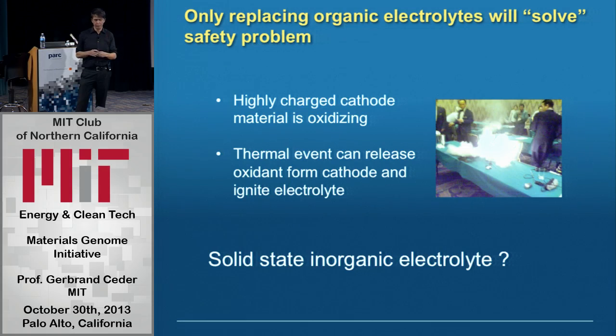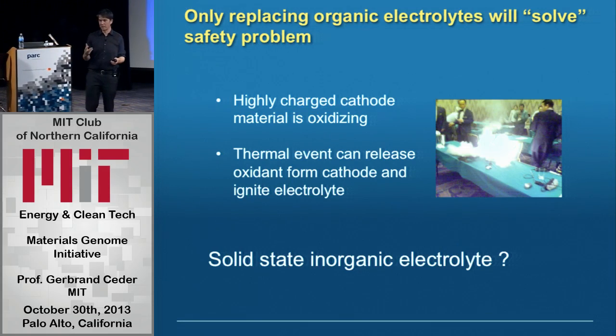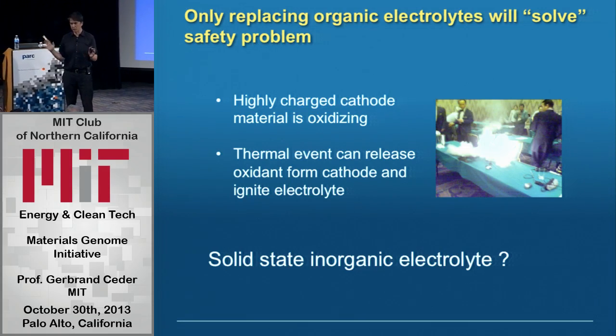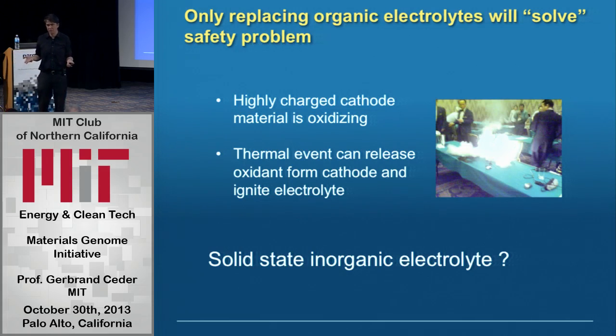There are two ways that a cell essentially can catch fire. If you puncture a cell and the electrolyte leaks out and it sees any spark, and remember, you often have high voltage sitting around with the battery pack, it will set off the electrolyte, and often the vapor of the electrolyte. The other way is that the cathode material is highly oxidizing when it's charged. So you basically have an oxidant and a fuel in a package together about 50 micron apart from each other. If you heat that up, it's an explosive. That's how you make explosives: you put the oxidant and the reductant together.